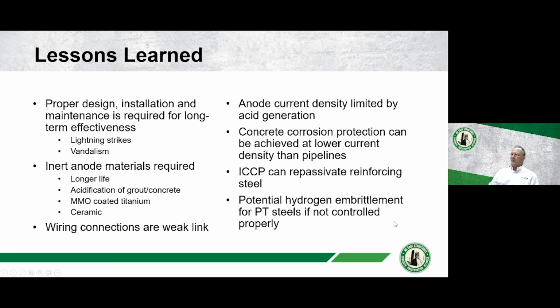Then we have this potential for hydrogen embrittlement for post-tensioning steels if it is not controlled properly. We're not going to get into that here today, but normally post-tensioning steels are a higher alloy, they're stressed a little bit higher, and they will become brittle if you run the potential of the steel too high. If it becomes more negative than minus 1.3 volts, the steel will become an electrode and will break down water into hydrogen and oxygen. And when you create hydrogen at the cathode, it will seep into the steel structure and can make it more brittle, causing it to fracture instead of yield.